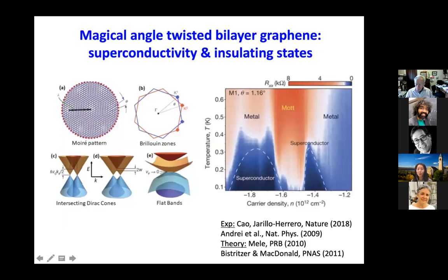So the experimental demonstration of Moiré and interesting physical phenomena was highlighted in works from MIT, Pablo, forgive me, I'm not going to pronounce his last name, from his group. What I'm showing here is that using the capacitor technique I mentioned, you change the gate voltage, and then you can introduce different doping. For a system at about 1 degree twist, you have a correlated insulating state. And then when you dope away from it, you get superconductivity.